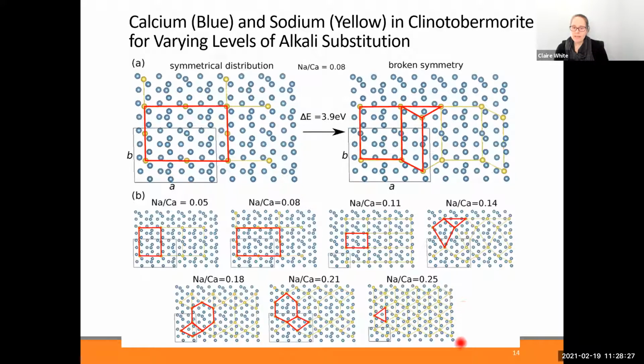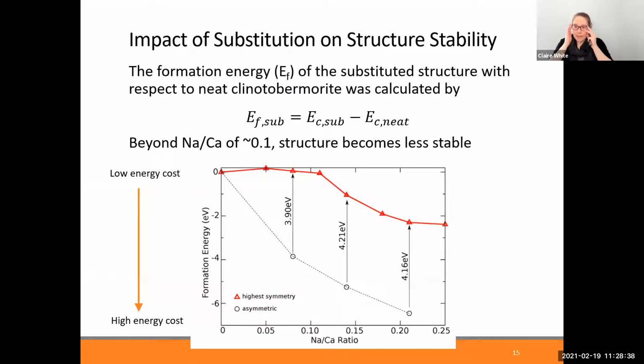So now what we're going to do is look at how stable these structures are relative to the baseline clinotobermorite structure that has no sodium in it. That's what's shown on this slide. We've defined something called the formation energy of the substituted structure, with respect to neat clinotobermorite, whereby we're taking the cohesive energy of the substituted structure and subtracting from it the cohesive energy of clinotobermorite. If the formation energy is 0, then the substituted structure is as favorable as the clinotobermorite. There's no energy penalty for having sodium in your system.